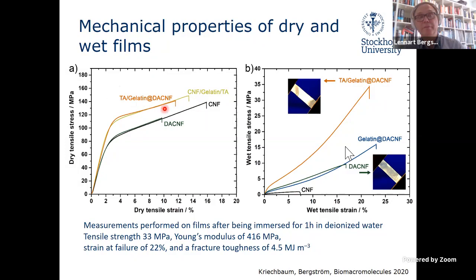The leather-inspired material we prepared has a little higher strength but a little lower strain to failure, so it's not a major improvement. The major improvement is, of course, in the wet state.